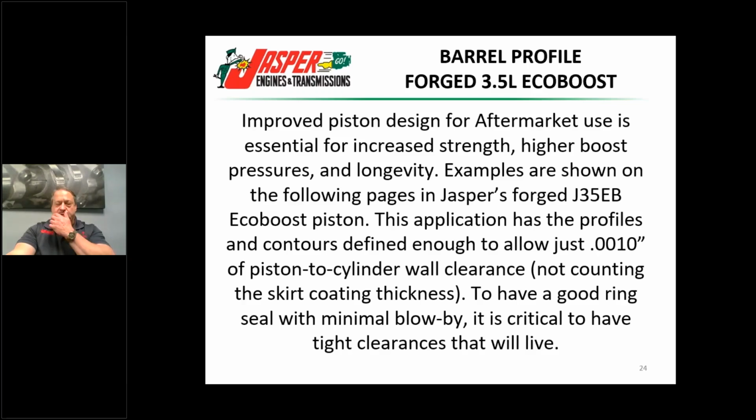Just for an example, I have a series of pistons here. This is Ford's first piston that they used. And there were a lot of problems with this, because the crown would come back in the second land and the major thrust is broken through just from heavy detonation. In 2011-12, they used the same piston, but they anodized the top ring groove. When you anodize the top groove, you harden it, you oxidize it in a controlled way. So if I had micro welding from the piston to the ring, then the anodization will help stop that.